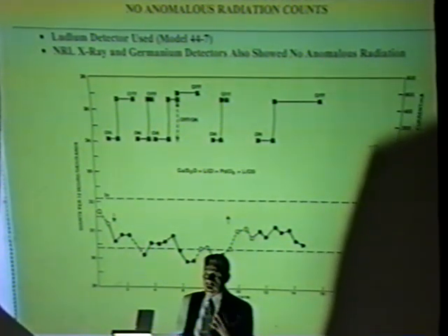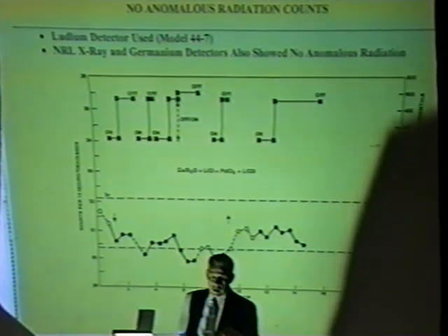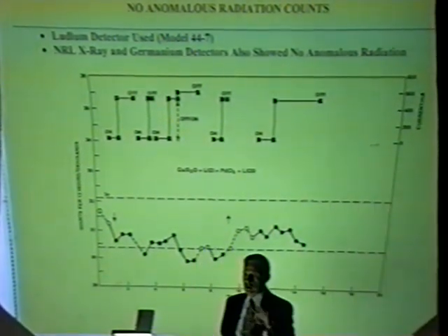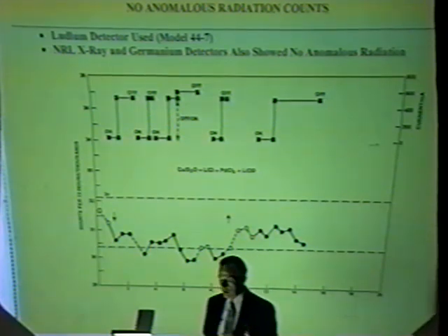And as I'll show later, that's perhaps the problem that we had, trying to do things too quickly and not allowing time to let the chlorine clear out of our system. The gases went through some tubing into an oil buffer, and so chlorine probably was still present in those gas tubings. And apparently, if you didn't flush those tubings out or give a couple of days time for the chlorine to dissipate, somehow this really drastically affected our results. At least that's what it seems to be. That is the conclusion that I finally came up with at quite a later date.